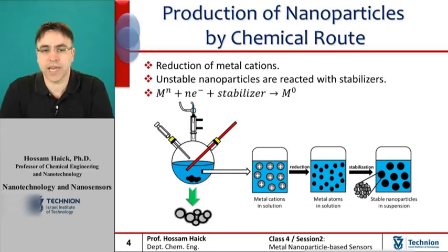Adding a stabilizing agent into this solution prevents uncontrollable growth of the nanoparticles, and gives control over the growth rate and also the particle size. Also, it can prevent agglomeration of the nanoparticles and can make the nanoparticles soluble in the desired solvent of interest.